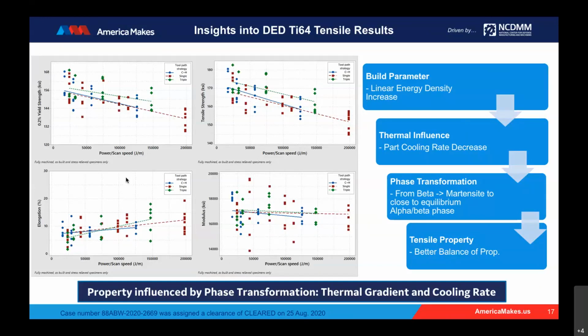So complementary to this downward trend, we typically expect an increase in elongation. That might be the case, but we have a lot of scatter in the elongation data, and that trend is not really apparent. So this behavior here we theorize is, with increasing linear energy density, we see significant influences on the cooling rate, which thereby affects the phase transformation from martensite to close to equilibrium alpha beta phase, which is then in turn reflected in the tensile properties here. So observations seen here make sense, and they are in line with some of the observations in literature.